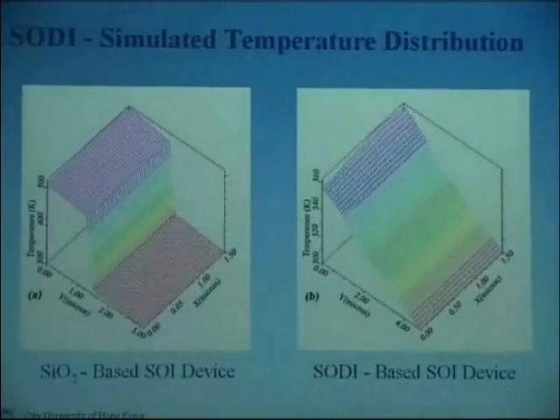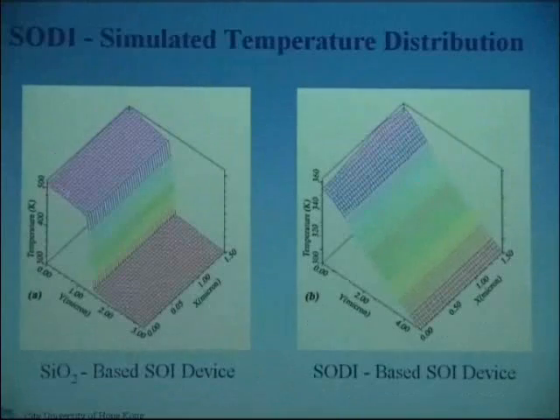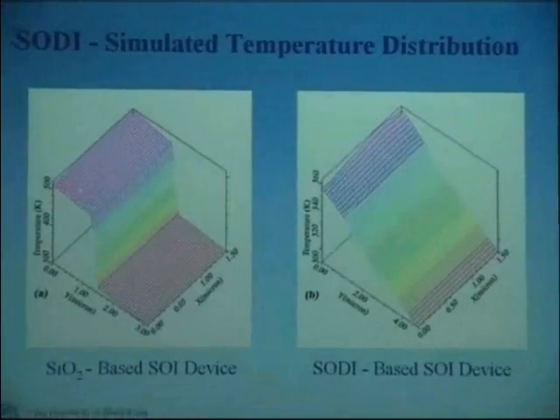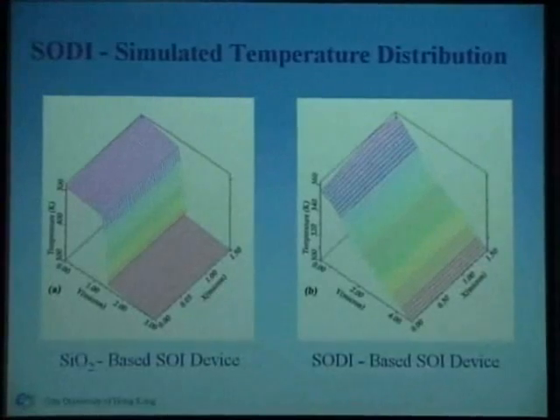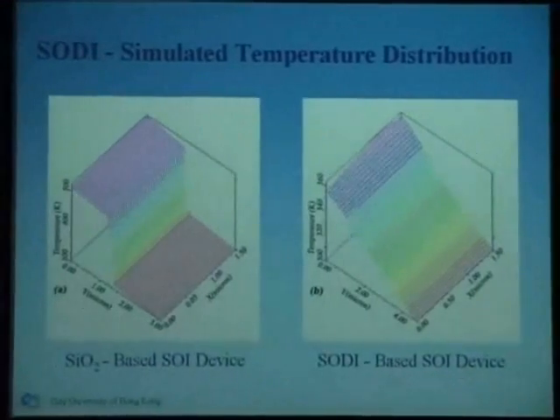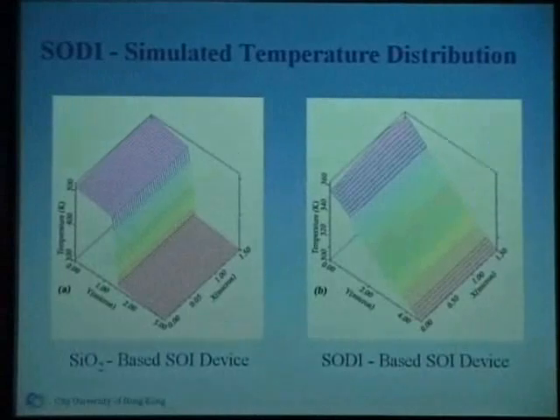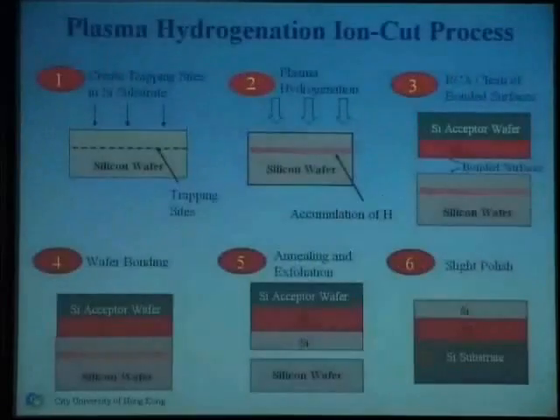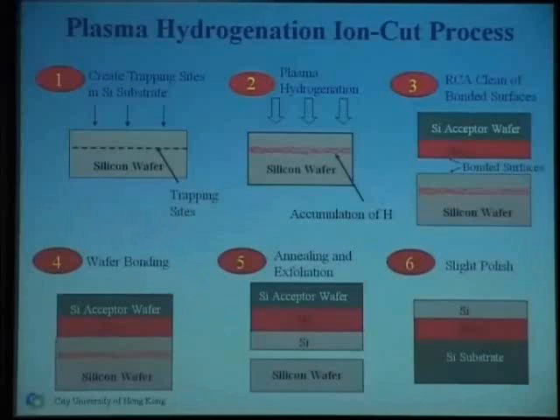And this is a simulation of the temperature. If we use the old technology, the temperature at the channel goes up to 500 K, which is about 227 degrees centigrade. If we use our SODI structure, 360. So that means that the heat problem is alleviated. It's a lot less than before. So very good. But we haven't stopped there because we want to make things cheaper.